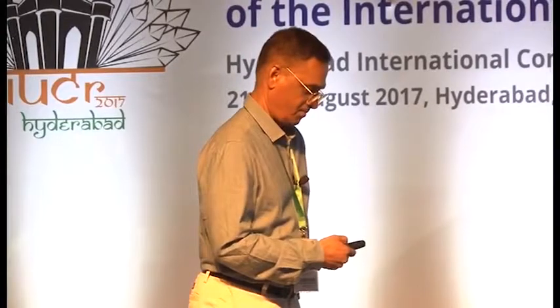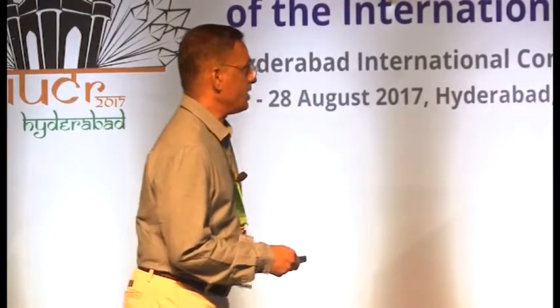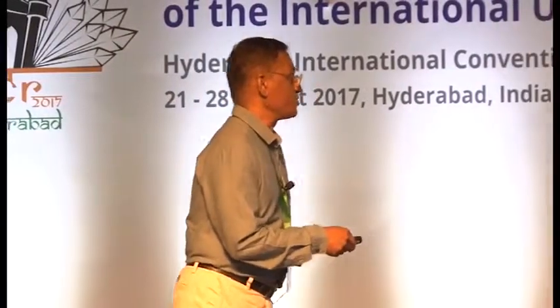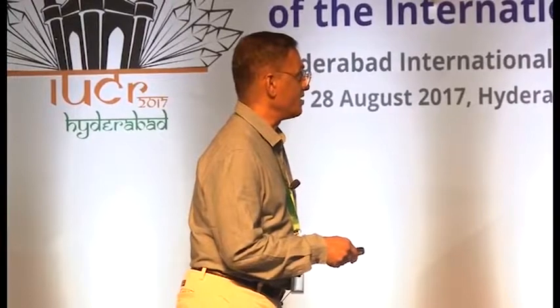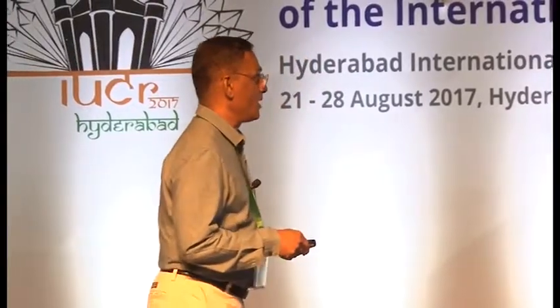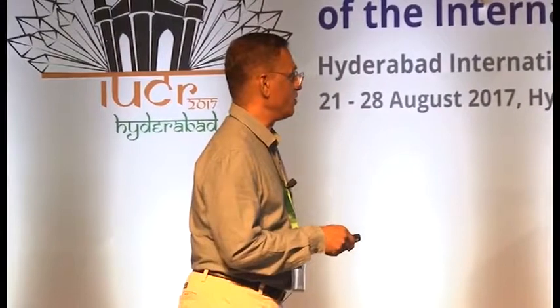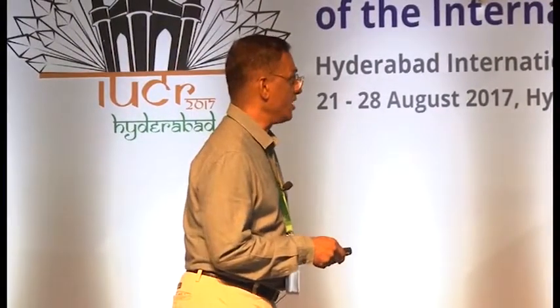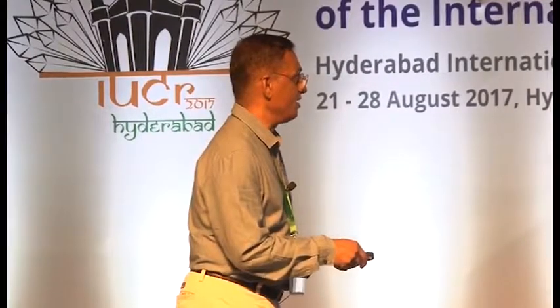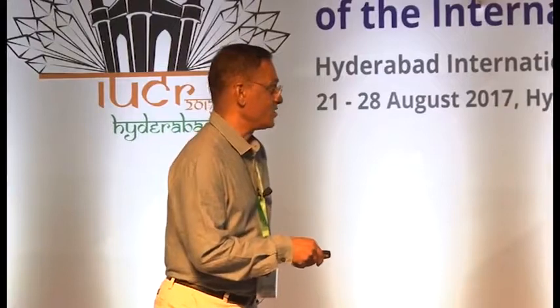Okay. And also we found out that this particular MOF contains this particular ligand with BDC. That forms diamondoid type of framework structures. And then when you try to put it in UV light for the double bonds to undergo 2+2 cycloaddition reactions, you get a polymer that is embedded inside the MOF, 3-dimensional structures. Actually, this was a 6-fold interpenetrated structure that goes to a non-interpenetrated compound that contains a polymer embedded very nicely. So it is a hybrid of both one-dimensional, 1D coordination polymer and then real organic polymer